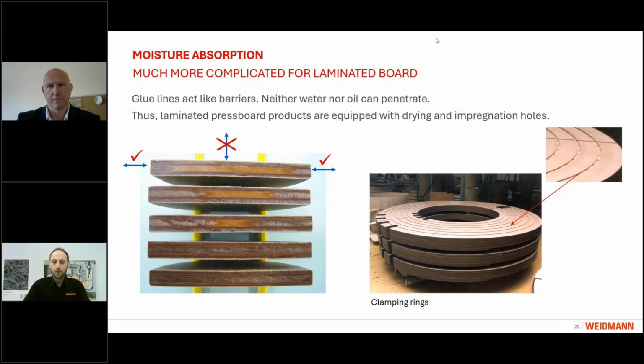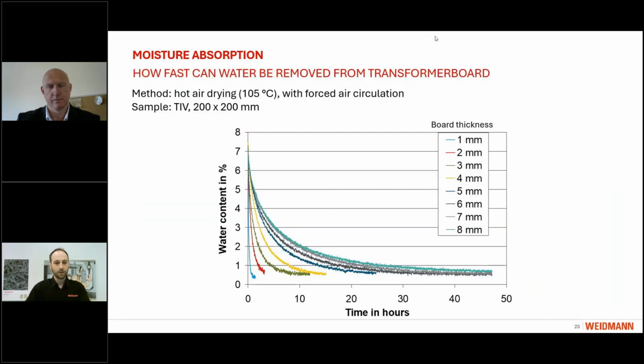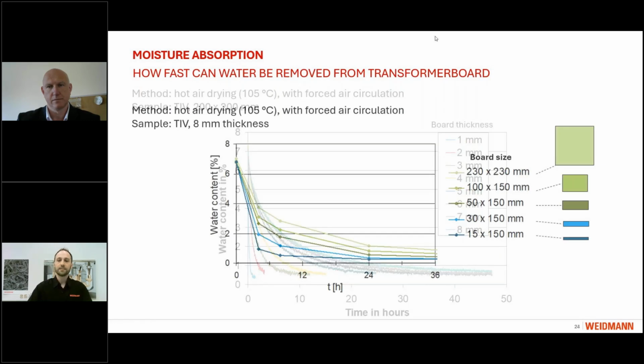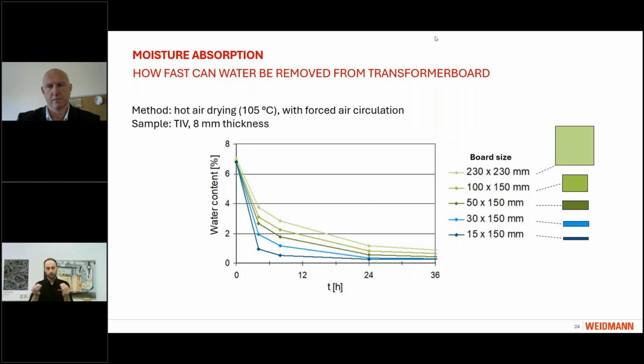Now that we know how it takes up water and what governs its processes, the question is, how can we remove it? And here again, we can see that, of course, the thinner the sample, the faster it is dried. However, what is also important is the area, because we have the diffusion process which needs to transport water to the surface. The distance of diffusion is critical. And with this 15 millimeter thickness, we are always quick, while with this square, the area in the middle remains quite humid until everything is then out.